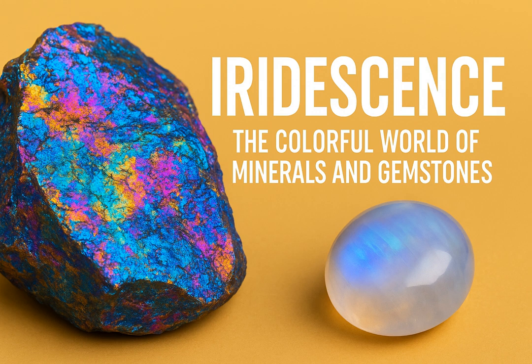This is explained by the earliest stage of segregation, where the orthoclase forms incredibly small crystallites first. These tiny particles cause a phenomenon known as the Tyndall effect. Tyndall effect? Like why the sky is blue? Exactly like that. Much like the way dust motes scatter sunlight in a beam, these tiny crystallites preferentially scatter shorter wavelengths of light, blue light, which predominantly gives rise to those vibrant blue hues we see first. Ah. Then, as segregation progresses, these crystallites grow into larger, more defined lamellae, the layers. These layers then become large enough to produce specific colors based on their thickness through interference, but they exceed the dimensions that would produce only those simpler, first-order Newtonian colors, hence the full, rich spectrum.